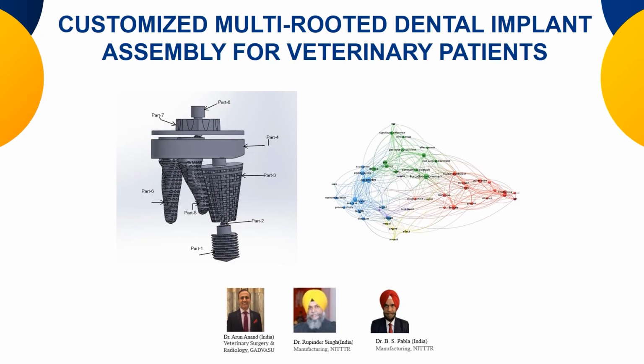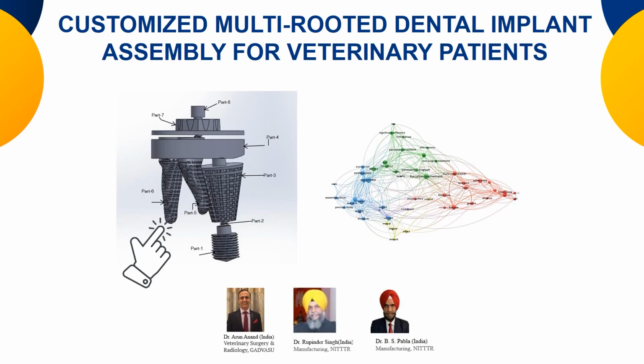This is the typical work for German Shepherd. Here the strategic tooth implant has been prepared, and in this case there are 3 roots. The typical application is that the load is to the tune of 800 Newton, whereas in humans it normally doesn't go above 80 Newton. So here it can be typically 800 or 1000 Newton. The natural phenomenon is that more roots are there, as you can see. So all these roots have been 3D printed and installed along with all the armamentarium. Again, the IPR is with us.